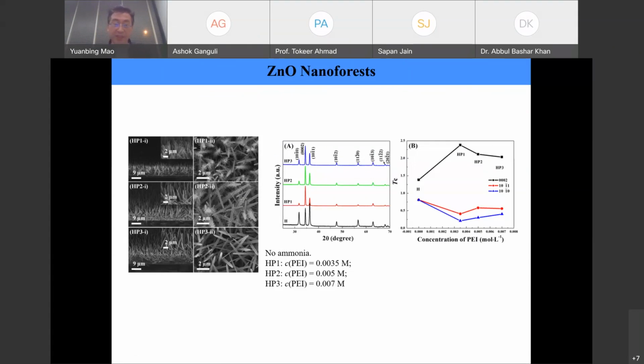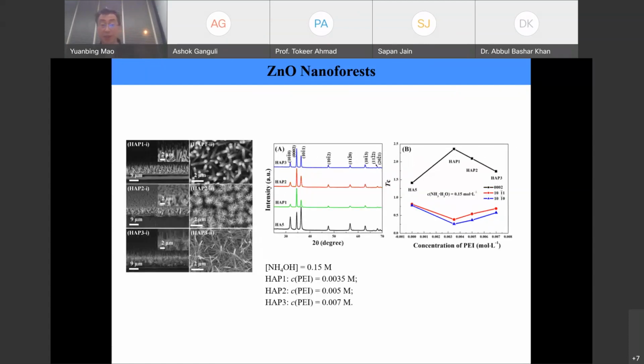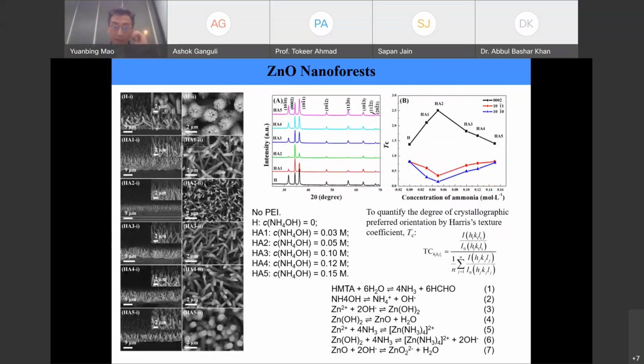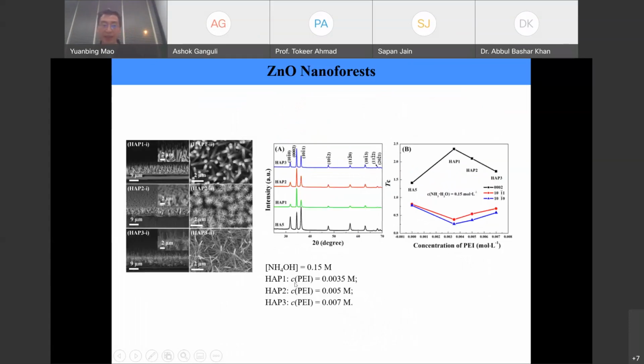Then the next thing is, okay, now we get a little bit of an idea of how the ammonia and PEI concentrations affect the branch growth. Let me get back to here. You can see that when the ammonia concentration is equal to 0.15 molar, the branches look nice, and those branches are thin enough, not like the first one. So that's why we picked this ammonia concentration, and then again we varied the PEI concentration, just like I showed you a little bit earlier.